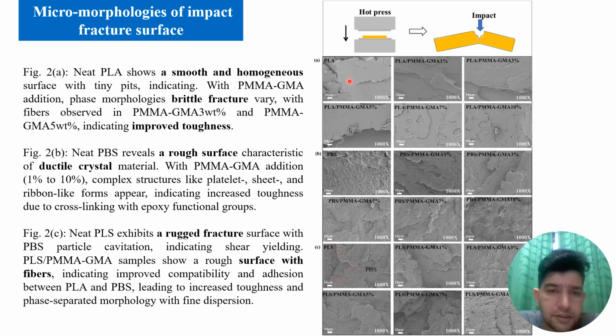Looking at the SEM images of the blend, also the PLA, PBS, and the blend. The PLA surface shows a very smooth and homogeneous surface with small tiny pits. So the surface is very smooth, which shows it is a brittle surface. While by adding 1%, 3%, 5% of the compatibilizer, the surface changes a little bit, showing some fibers also on the surface of PLA, so the brittle surface varies, which shows the improvement of toughness, because from the surface we can say that the toughness of the PLA is improved because of the compatibilizer.